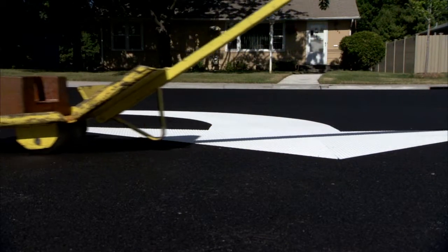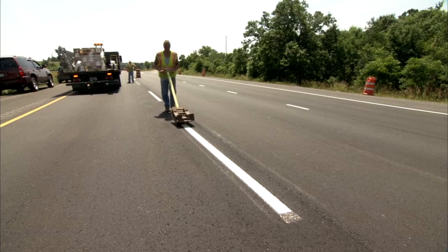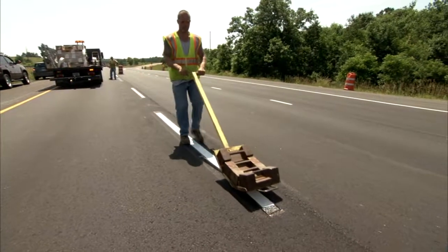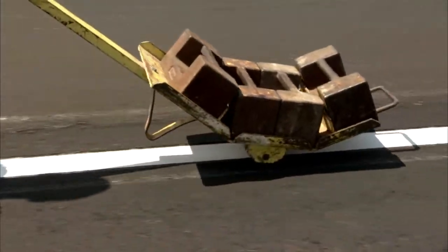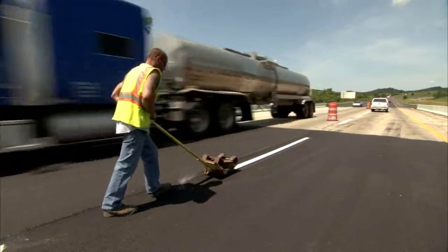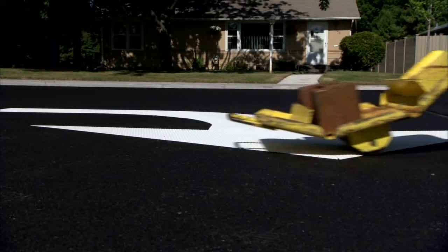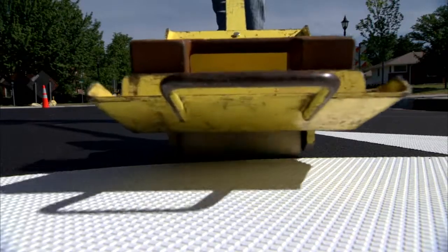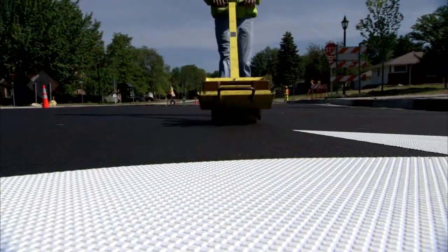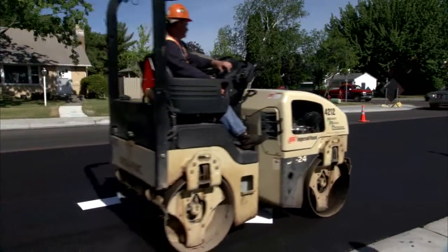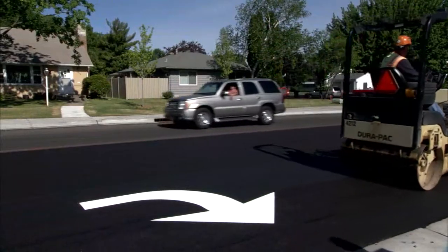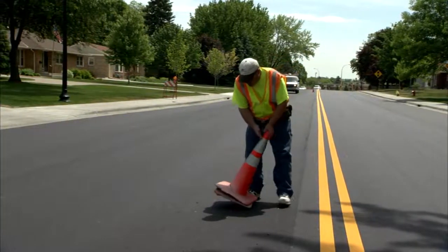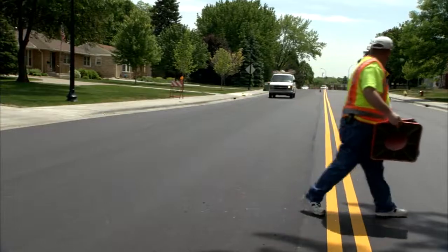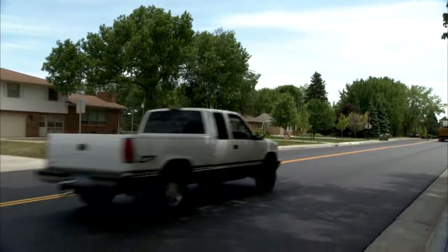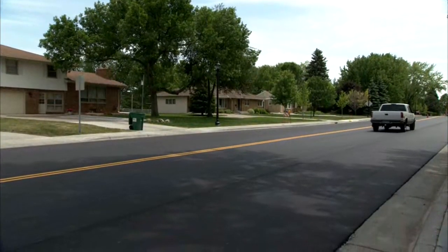Hand application of markings requires a pre-tamping step to set markings prior to inlay with a finishing roller. Pre-tamp using a roller tamper cart with up to 100 pounds of weight. Transverse markings should also be pre-tamped, using a smaller amount of weight on the tamper cart if necessary, to prevent buckling. When embedding transverse markings, roll perpendicular to the marking. The road may be open to traffic as soon as the inlay application is complete and the asphalt has cooled to temperatures that support vehicles without surface damage.